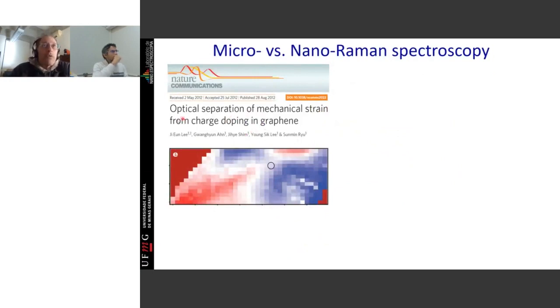There is an interesting paper that was published in 2012 by some Korean fellows, where they show that if you look into the frequency of vibration of some Raman peaks in graphene, you can characterize strain and doping, okay? And if you use two frequencies, like we did for line defects and point defects, if you have two pieces of information, you can disentangle doping from strain. And then they do it nicely for a sheet of graphene. So what you have colorized here is a sheet of graphene, and the different colors are different strain and doping, okay? But this was done with a microscope, and every pixel you have on this image is actually 1 micron.